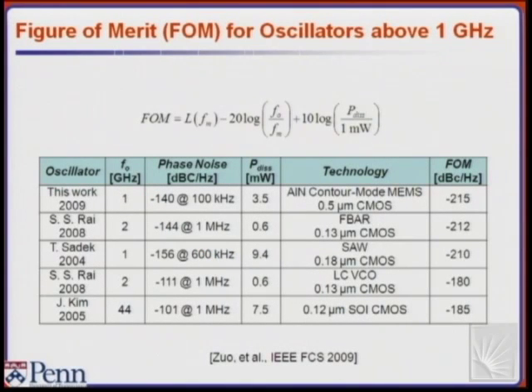And another way to compare, actually we put together, basically we use what is an accepted figure of merit for this oscillator, and basically it takes the phase noise at a certain frequency offset, scales it for the frequency of operation and for the dissipated power, and creates this figure of merit which is measured in dBc per hertz. And actually we compared with other oscillators made at 1 gigahertz or in the neighborhood of 1 gigahertz.